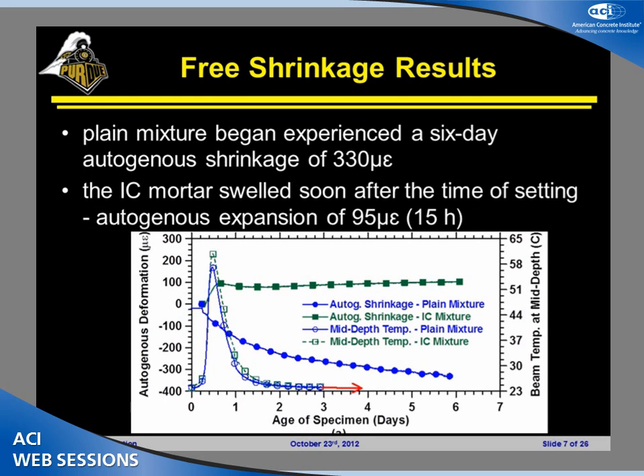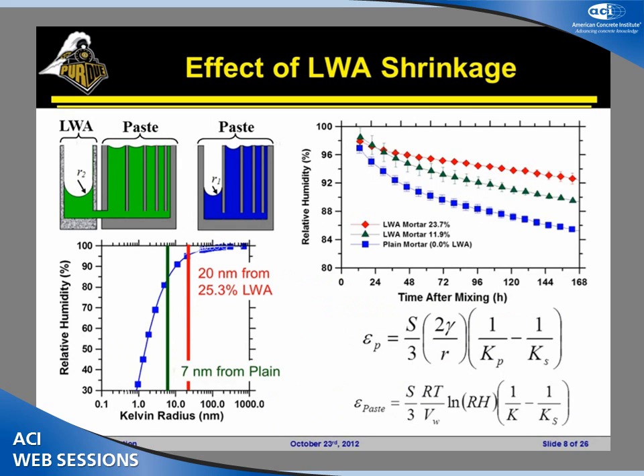Now, I'm not going to talk about this temperature part quite yet. I'm going to talk about it in a second. But what I want to do is, for the concretes that we're looking at, this is the shrinkage that we're seeing in the plain concrete. Again, by the time we get out to about 6 days, we've got 300 microstrain of shrinkage that's built into the system. This is the internally cured concrete. And as we talked about a little bit earlier in the session, this reduction in shrinkage, this slight expansion, is due to the fact that we're moving water from the lightweight aggregate into the paste.